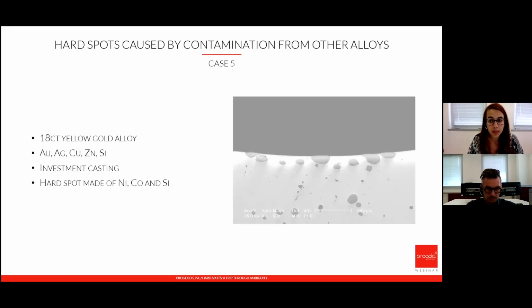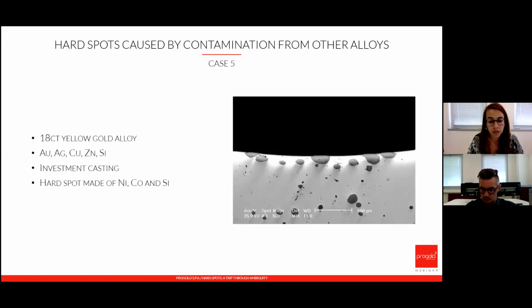The first one is because we are not using different crucibles for different alloys. Even if we think that our crucible or die, our whole set that we're using for melting, is clean, there's always some traces of the elements that we melted before that remain inside the material. And when we heat up, we actually favor some mechanisms that tend to put these old elements inside the new elements, even if we're starting with fresh metal.